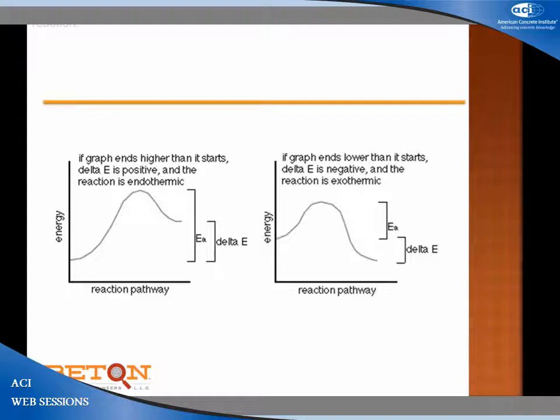We also know that we have to push. We need an activation energy, which is why concrete is self-stoking. Exothermic reactions that have a relatively high activation energy, in other words, the Gibbs free energy is different, so you've done well, but you've had to get over this hill. Self-stoking reactions are very interesting because the hotter it gets, the faster it goes. The faster it goes, the hotter it gets, and it goes on and on like that.